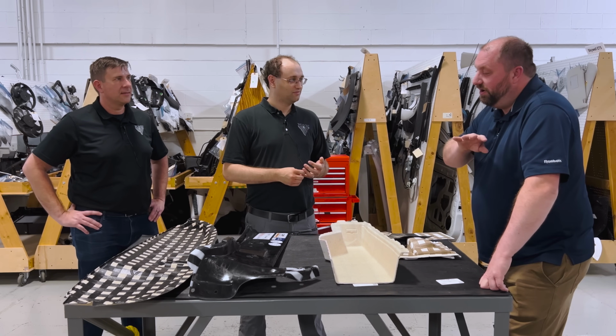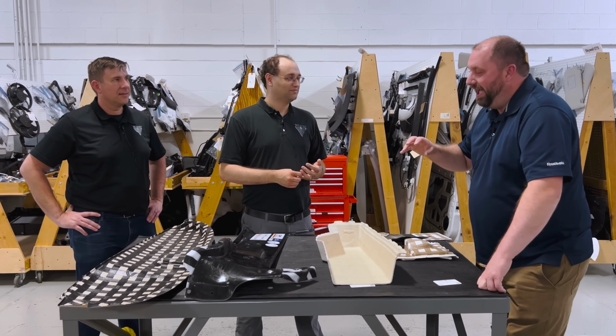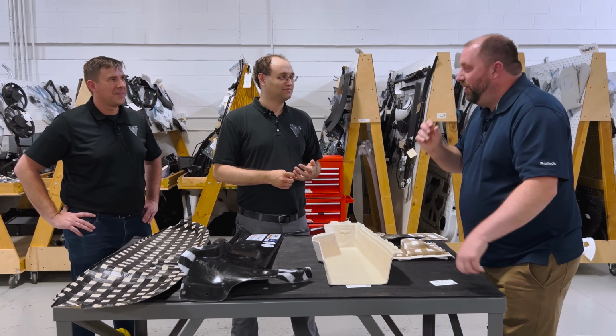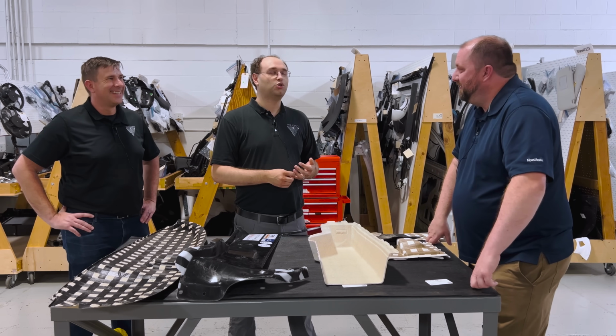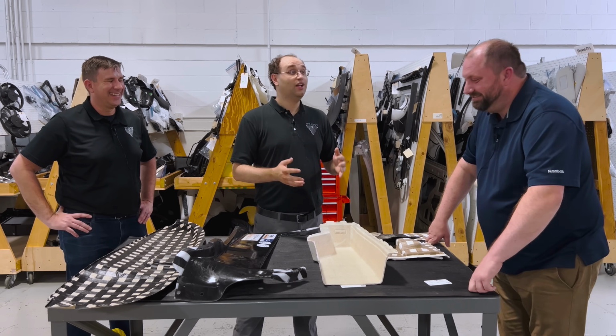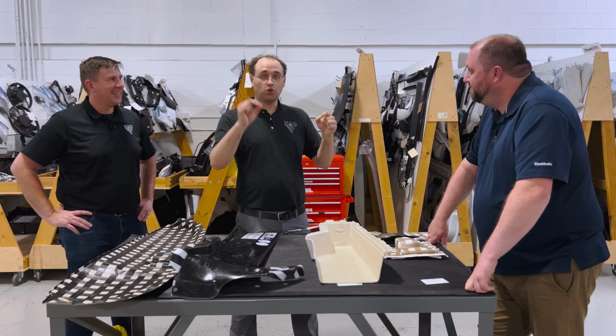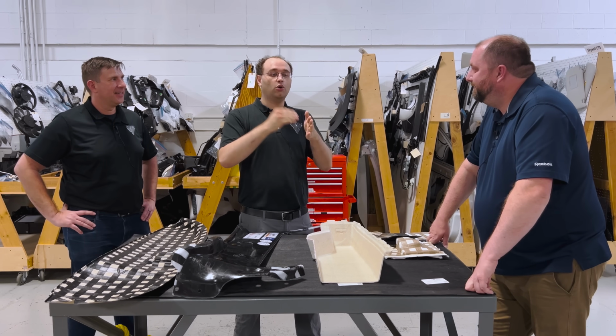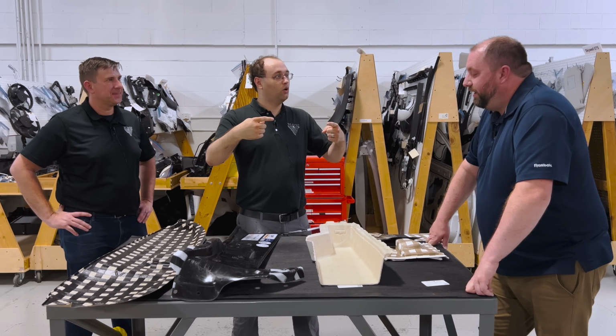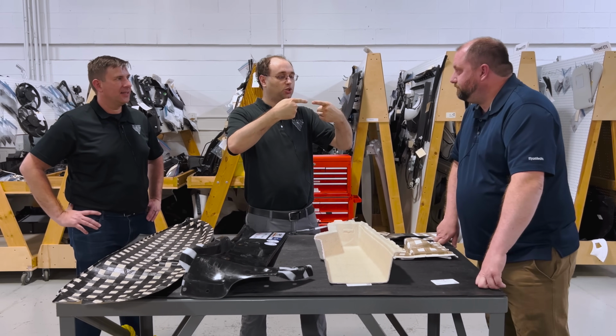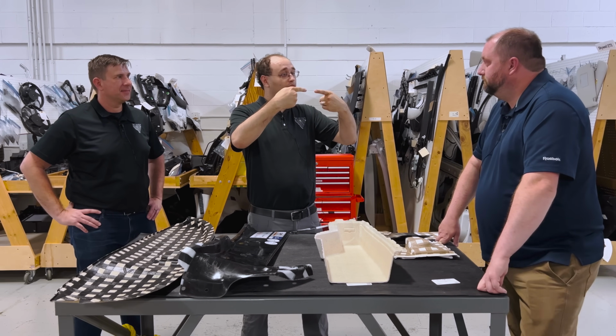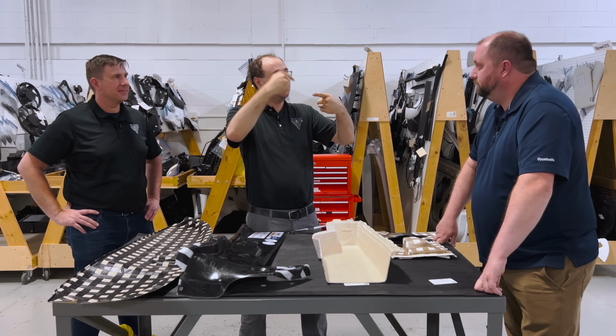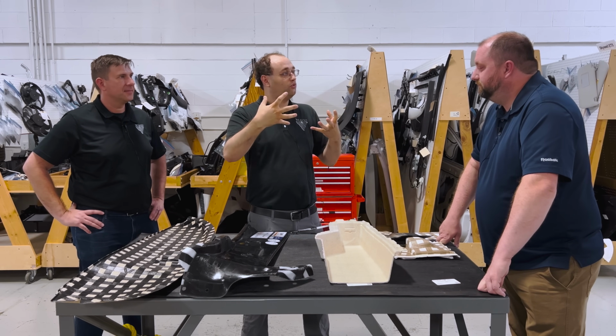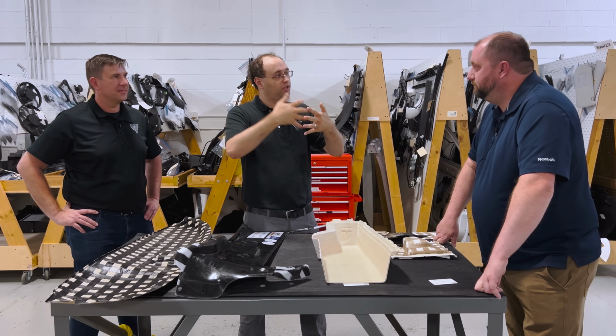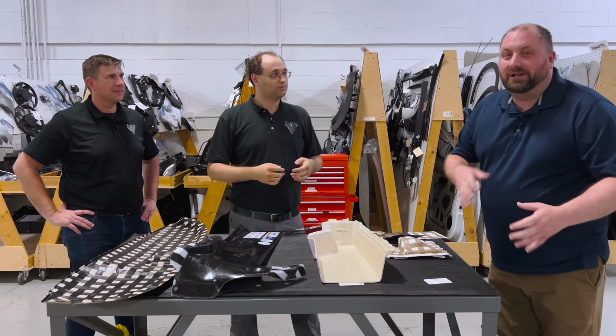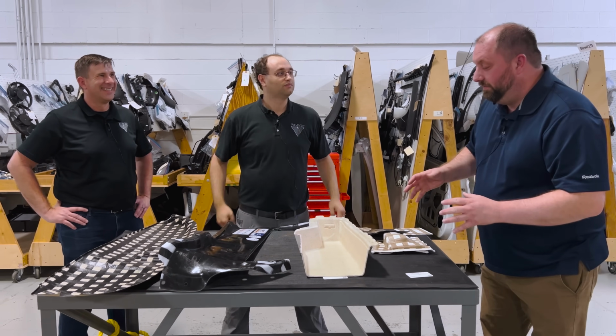Then we burnt all the resin off to try and find out as it's going through the screw coming out, what are we left with? 0.2. So my short average. There's so much attrition. Yeah. So this is a problem though, because the shorter the fiber, the less load transfer you have from fiber to fiber. So if you've got two fibers that are really short, that there's a gap between them, then the load has to go through the polymer to get to the next fiber, and you're losing performance because you're not cohesively transferring load. So a little bit more on the nerd moment.